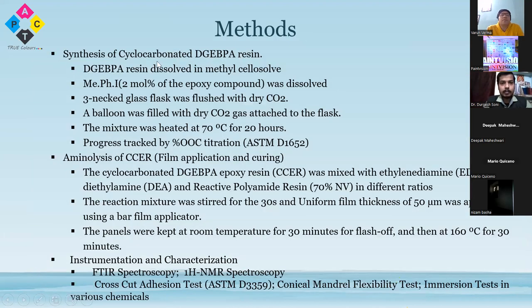So synthesis of this cyclocarbonated epoxy resin was like that. And the resin was dissolved in the solvent methyl cellosolve. And then 2 mole% of the epoxy compound, the catalyst, was dissolved in this.